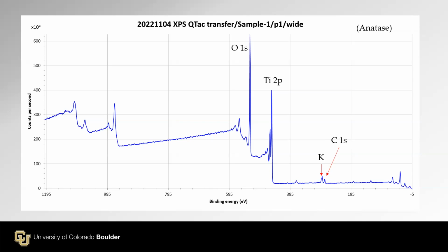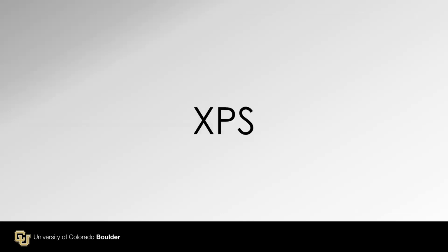But when you see the XPS spectrum, okay, contamination of potassium as a minor element, it looks like, but in reality, this powder surface is really covered by potassium oxide, I think. So those are differences. And I try to cover more about LEIS next week.